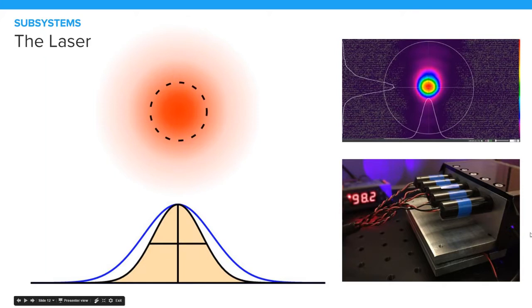You can actually pick up handheld versions of this type of laser for anywhere between $5 and $240 on the internet, depending on quality and power output. But it's really useful to have these around the shop because you can dab some uncured resin onto your part, and then if you hit it with the handheld laser, the laser will cure the resin. You can use it like a sort of glue for your printed parts. So if you ever have to split up a part to fit it into the build area, it's a good idea to have one of these lasers around.